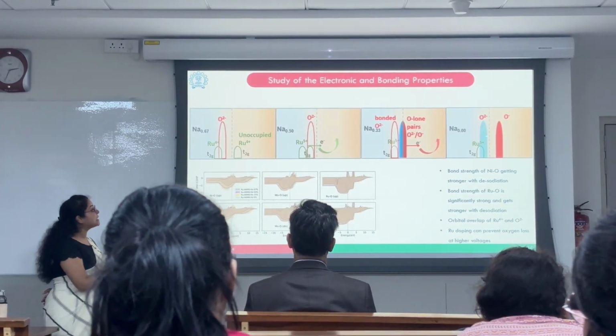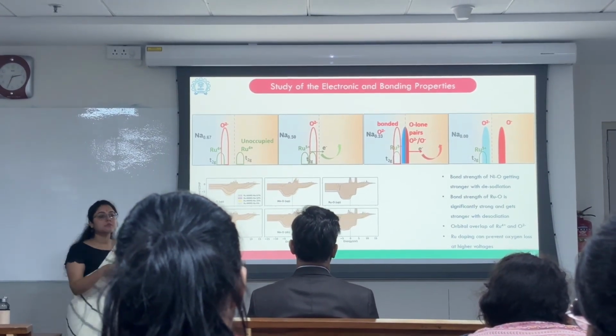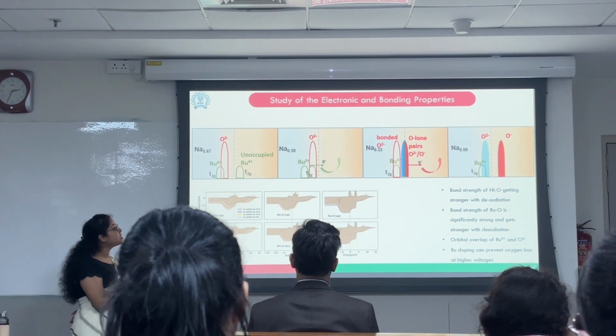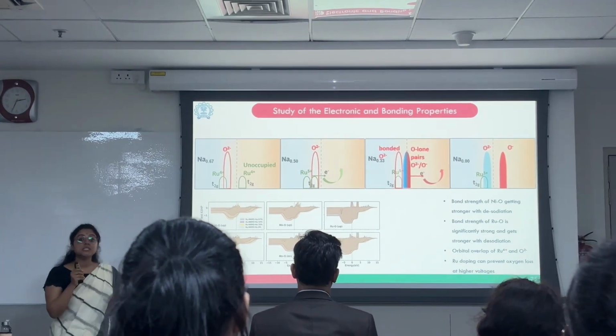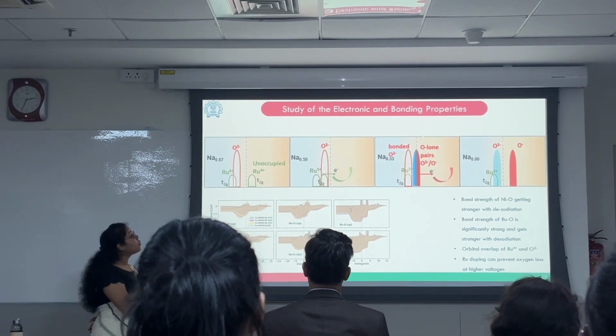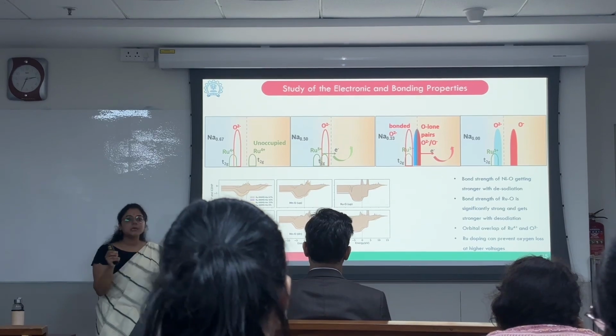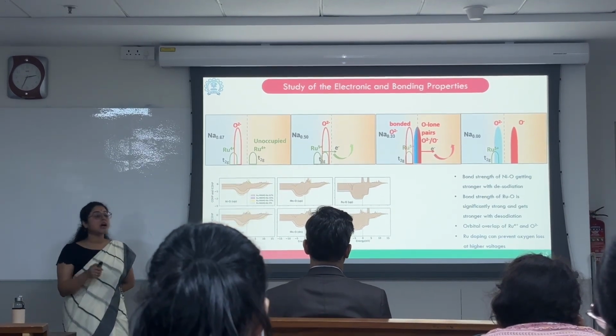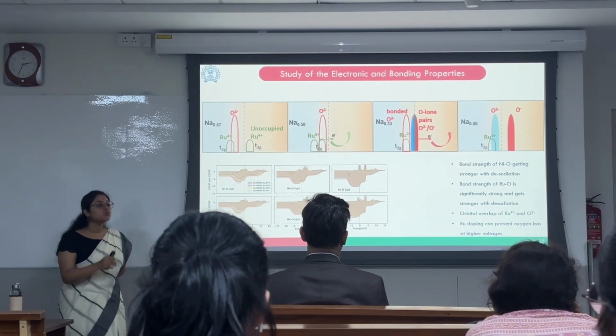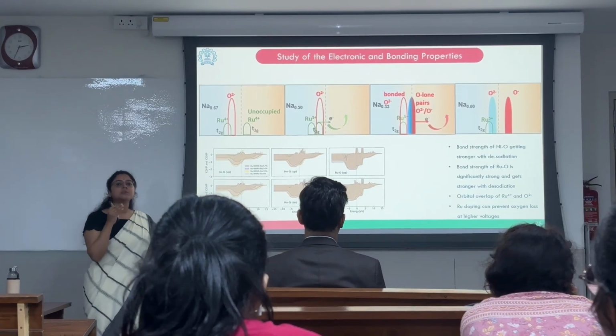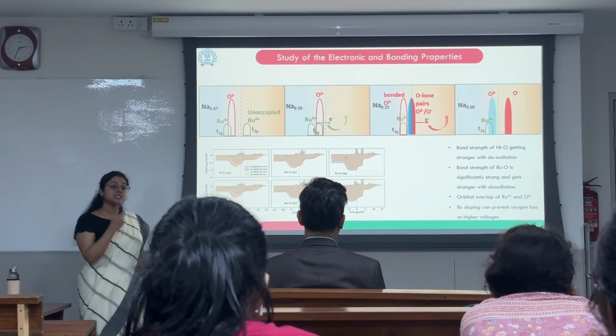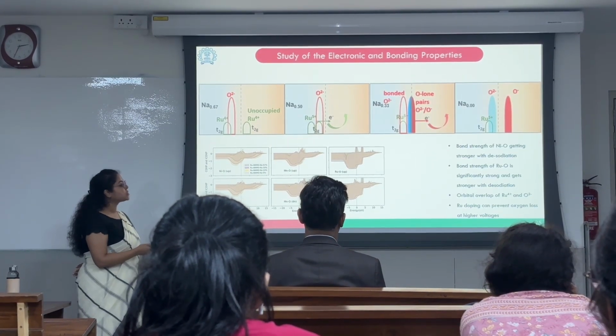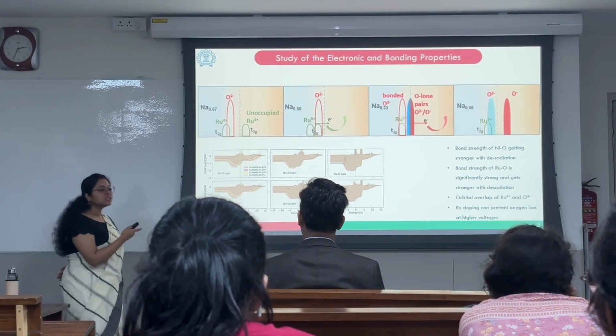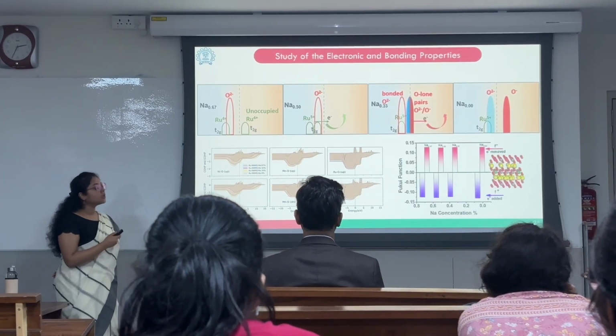And not only that, at 0.33, when the sodium ions are extracted and the anionic redox reaction is initiated, we see that we get bonded O2 minus, which, in comparison to that of the alkali-rich material, are underbonded, which leads to loss of oxygen from the lattice, which is a disadvantage. In this case, we have improved that. And we further verified that through the Fukui functions.